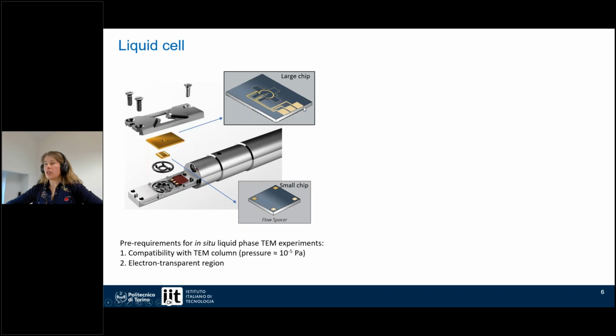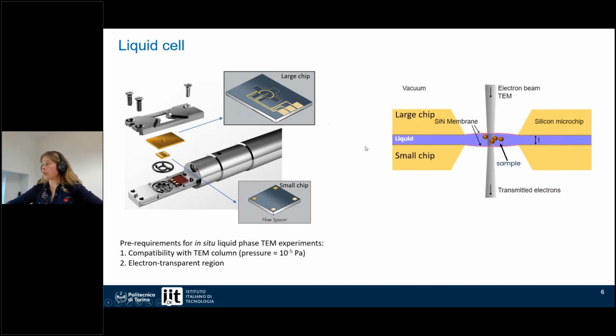Both chips have a spacer incorporated in them, which will define the thickness of the liquid layer on top of the working electrode and in general in the cell. And the electron transparent region is defined by a suspended silicon nitride membrane, which is here in the central part. And this is how it looks when we look at the cross section. So we have the large chip with its silicon nitride membrane, the small chip with its membrane, and the liquid in between those.